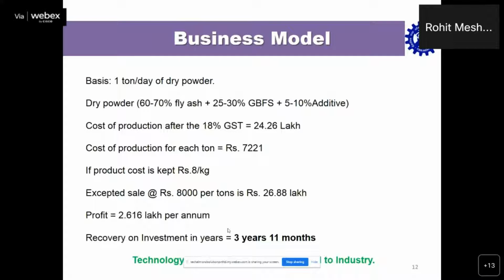And this technology, as I already mentioned, is demonstrated and transferred to the industry in Hyderabad. There are three advantages for the industries. It reduces the greenhouse gases. You already know that 1 ton of cement emits around 870 kg of CO2, and for the geopolymer quick repairing material, it is around 350 to 400 kg of CO2 per ton. So it is very less. It also helps to preserve natural resources like limestone, and the cost is also minimum because we are using waste and byproducts.